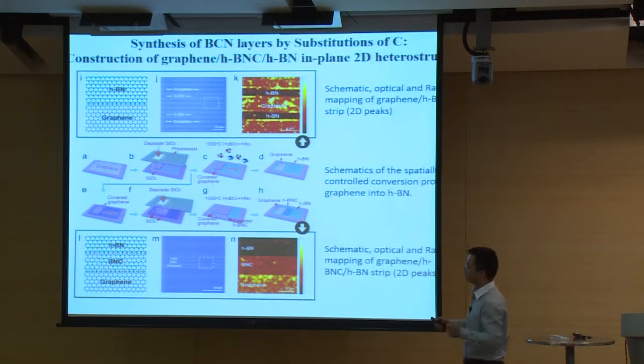And okay, furthermore, if we protect part of the graphene areas and convert the rest of the areas without coating, we can convert these exposed areas to boron nitride, and after we remove the protector, we get a graphene-boron nitride hybrid structure again. This is also shape engineering. But we can go to the next step, where we protect some areas and convert others to BCN, and convert some other areas to h-BN. So in a single layer, we can get graphene, boron nitride, and BCN, three different compositions in a single sheet.